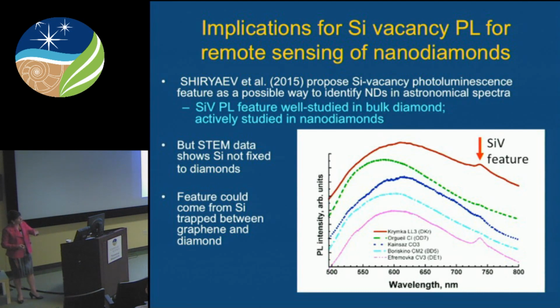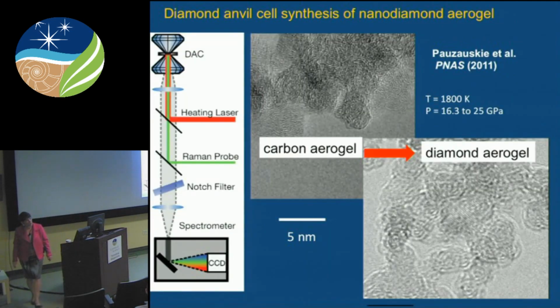So I think this vacancy feature could be equally well attributed to the fact that they've got a coating of sp2 carbon over the nanodiamond. This is annealed, and although this feature is well associated with incorporation of a silicon-vacancy complex into the interior of the nanodiamond, this boundary between graphite, nanodiamond and silicon is not that well understood at this point, and I think this is an equally likely observation.